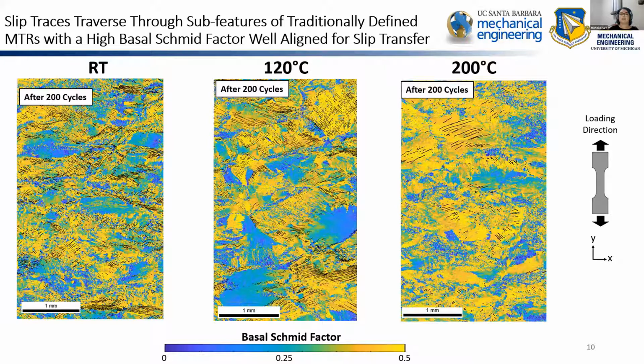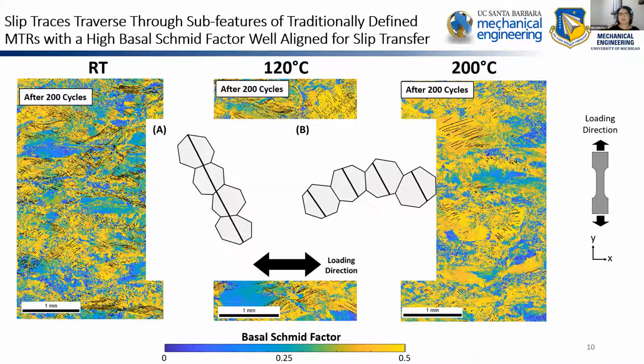And the other thing is that they are co-located. They're regions where we have this easy transfer of our basal slip. And so something that's important to note is the spatial location of those grains. In figure A, we have the idea of them being co-located, and we also have our parallel alignment of our basal slip plane for easy transfer. And they're well aligned so that they can transfer from one to another. In figure B, while we still have parallel basal slip planes and co-located grains, those basal planes are not aligned well for slip transfer, so we're not going to obtain those long-range slip features.